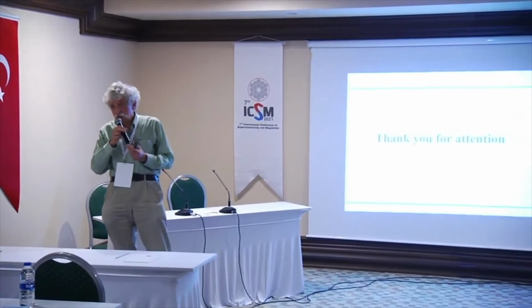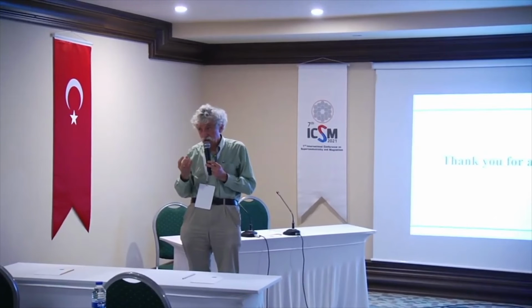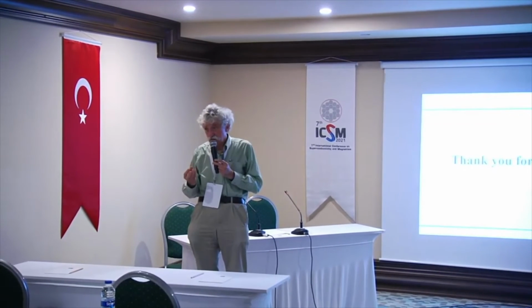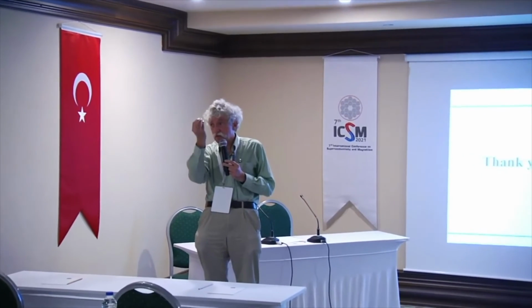There are several technical details which I didn't show. The material is made so that the intercalation is not stable in time at all. So immediately after intercalation, the sample is put in a quartz tube. Inside this quartz tube is a quartz rod, the sample is put against the quartz rod, and there is another quartz rod. So the sample is completely fixed, and the quartz tube is closed. This sample is never in air. All the time it is in the quartz tube. It is never removed. So all of the measurements on this intercalated material are only magnetization measurements, because we were afraid to remove it. And if you repeat this measurement after maybe 1 year, you will still get the same results. So I think the sample is not destroyed in this way.